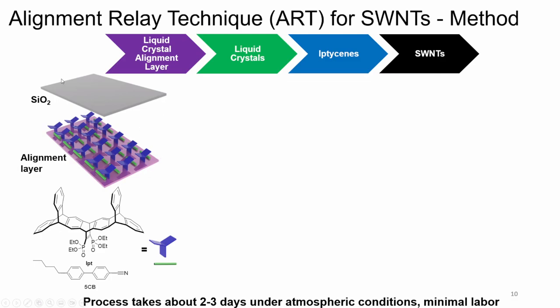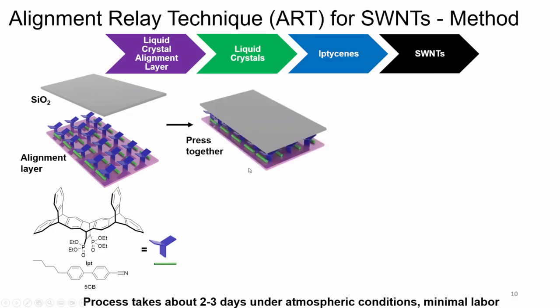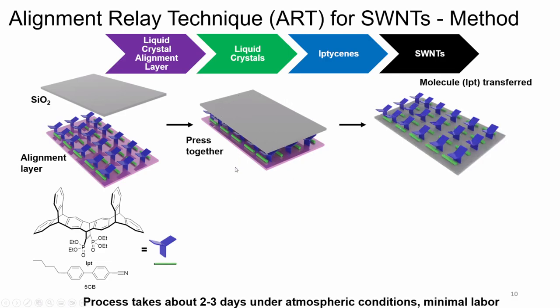Then we place an oxidized wafer onto the surface, SiO2, the silica, and we press the two together. As I mentioned on the previous slide, we have that covalent bonding, the displacement reaction that happens between the oxidized substrate of the silica and the phosphonate groups of our iptycene molecule. So the two combine here. This reaction takes about a day or two to complete. Then the iptycene molecule, the blue one here, is transferred, all aligned, onto the surface of our target substrate, the silica.